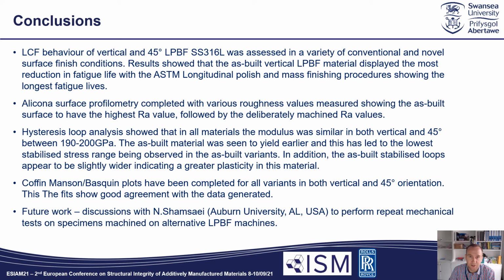Hysteresis loop analysis showed that the as-built materials seemed to yield earlier, and this led to the lowest stabilized stress range being observed in the as-built variants, and also the greatest level of plasticity, which contributed towards the lower lives of the specimens with this finish. The Coffin-Manson-Basquin plots have also been completed for all variants in both vertical and 45-degree orientations, and the fits show good agreement with the data generated, but again, more data still needs to be gathered to really iron out the robustness of these curves.